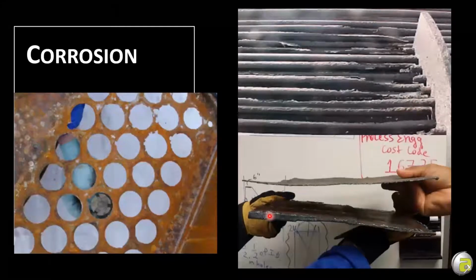And this one is a tragic one. This is a regenerator column in a plant in the United States. This is the original thickness, and this is the thickness of the plant after 1 year of operation. It actually even punched holes in the side of the regenerator column. And this was caused by high heat-stable salt, aggressive heat-stable salt attack on the steel.